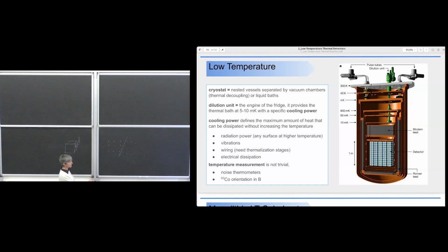So the cryostat is the set of nested vessels. There are two vacuum chambers in between some of these vessels. One is called the outer vacuum chamber and the other is the inner vacuum chamber. They are made of a material with high thermal conductivity. Insulation is obtained with vacuum. You have to be careful, because this is the region where you reach 10 millikelvin. The cryostat hosts a pulsed tube to cool the shields at different temperatures. These nested vessels are called the thermal shields, and when you move from outside to inside, each shield has a lower temperature.